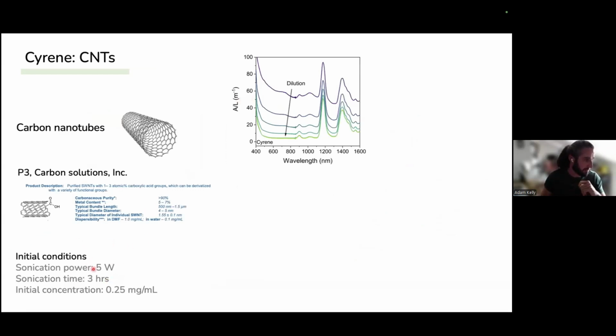As we move on to looking at carbon nanotubes, we need to be careful to work at a sonication power that's only 5 watts. We picked an initial sonication time of about 3 hours and a starting concentration of 0.25 mg per mL. The carbon nanotubes that we're using are from P3 Carbon Solutions, a company in the States. The typical diameters are about 1.5 nanometers and they arrive in bundles.